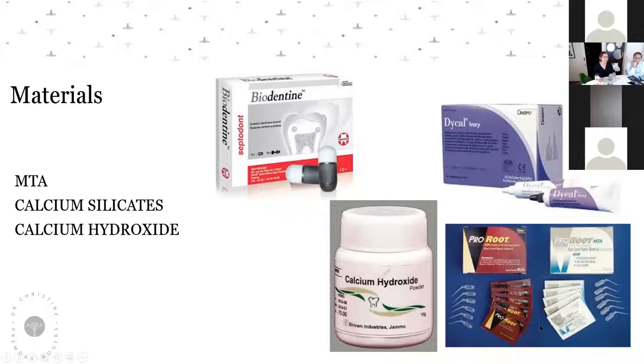You have to leave a dampened cotton wool pledget on top of your MTA so that it will set with time. And at the second appointment, you need to check that you have a set material before you place any other materials to restore the tooth. Biodentine, as I said, usually sets between 9 to 12 minutes. So you can actually do it on the day and place your permanent restoration.